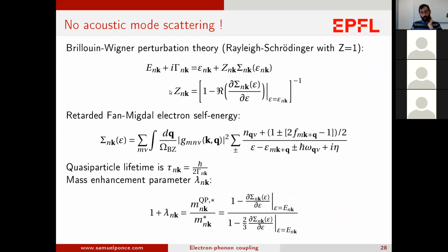And so what we did in that paper is that we showed that one could reproduce very accurately the ab-initio result with a very simple Fröhlich-based model. And so if we use Brillouin-Wigner perturbation theory, we can show that the renormalized eigenvalues, this is the real part, and this is the imaginary part, so this is linked with the broadening of the state, are equal to, let's say, the DFT eigenvalues plus the electron-phonon self-energy evaluated at the DFT one, but then you need this linearization, because in principle, the self-energy should be evaluated at the renormalized eigenvalue. So this should be solved self-consistently, but you can approximate that with this renormalization factor. Also note that you get the Rayleigh-Schrödinger perturbation theory if you assume Z to be 1.